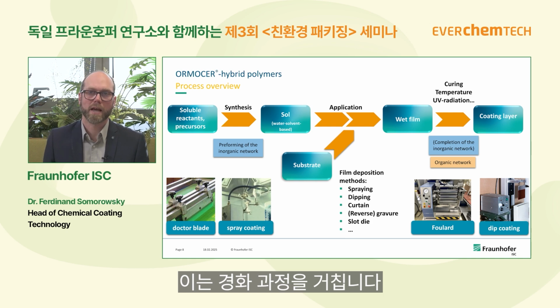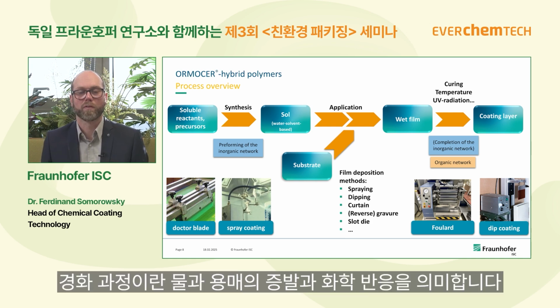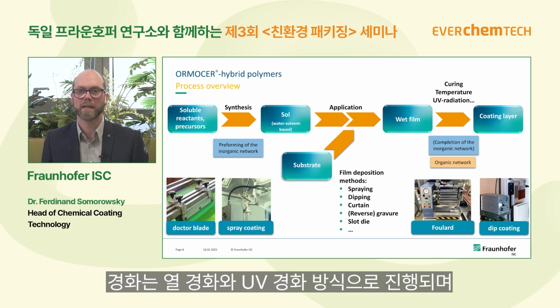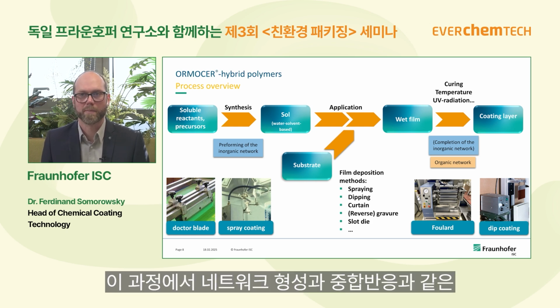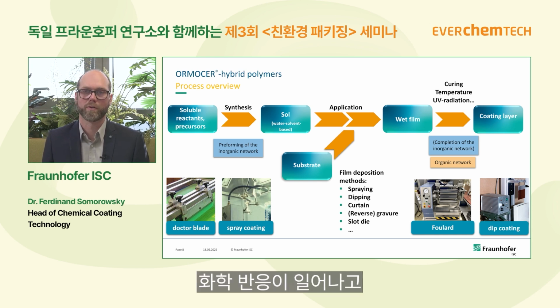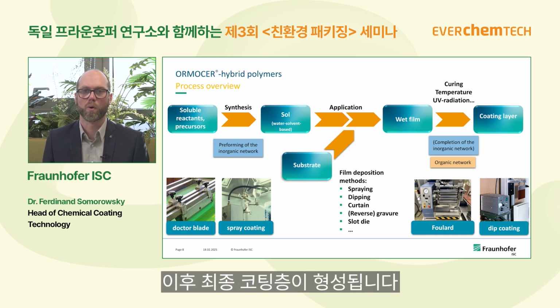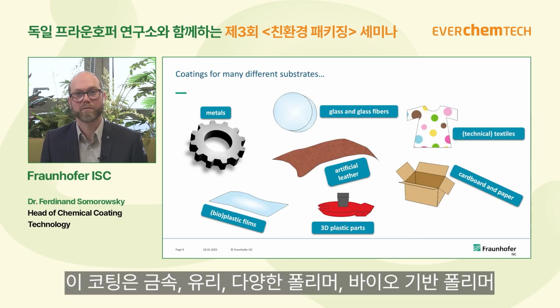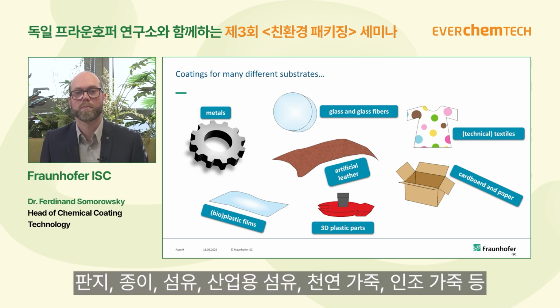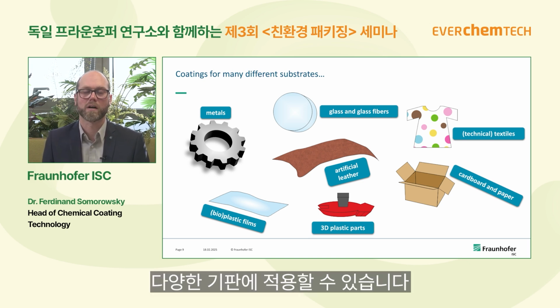Curing in this case means evaporation of the water and solvent and also a chemical reaction. So this curing, a temperature curing or UV curing, causes a chemical reaction and, for example, a network formation, a polymerization. And then we have our final coating layer. We can coat many different substrates, starting from metals to glass, different polymers, also bio-based polymers, cardboards, paper, textiles, also technical textiles, and even natural and artificial leather.